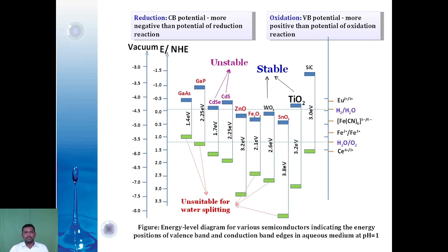This is the overall band edge diagram of various semiconductor materials. Here we have taken gallium arsenide, gallium phosphide, cadmium selenide, cadmium sulfide, zinc oxide, iron oxide, tungsten oxide, tin oxide and titanium oxide. Out of these various classes of materials, titanium dioxide and tungsten oxide are found to be mostly stable against anodic corrosion, and also stable under long-time illumination. Whereas cadmium sulfide and cadmium selenide are found to be unstable, even though their band gaps are 1.7 electron volt for cadmium selenide and 2.25 electron volt for cadmium sulfide. Though the band gap of the material is small, it is found to be unstable.